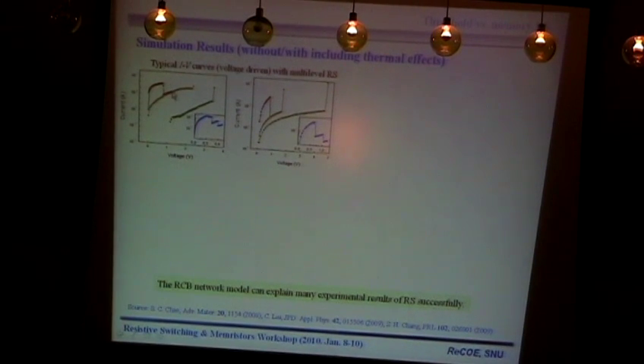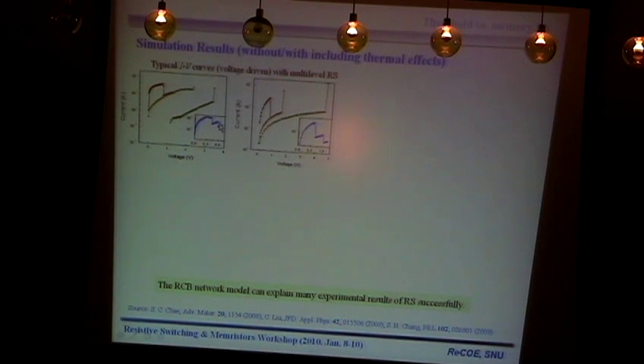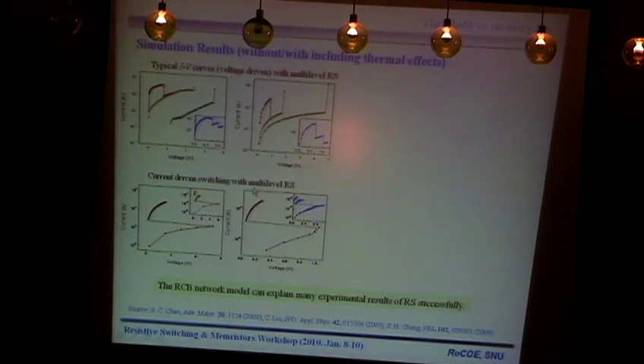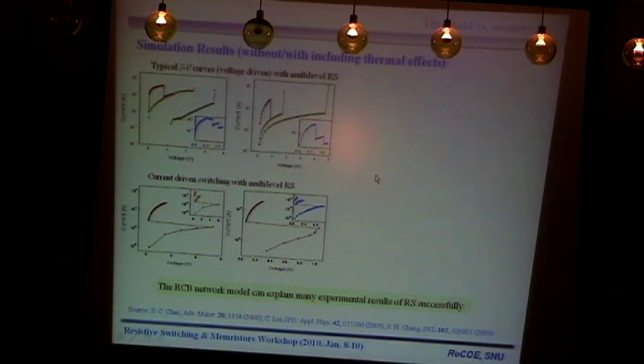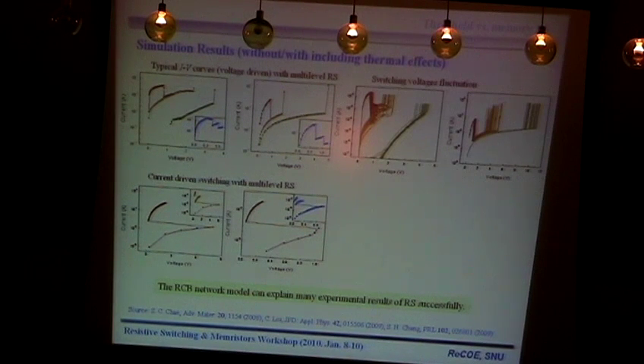First, this is the typical IV characteristic curve showing forming and the reset and set process. Sometimes it shows multi-step, multi-level switching. The simulation can show the same thing, and if you change the initial defect configuration a little bit, sometimes you get multi-step, multi-level resistance switching. Also, this is current-driven switching, which was first done by Samsung, and you can simulate the same multi-level resistance switching with current driving. A lot of people also reported a wide distribution of the switching voltages. The simulation can give exactly the same thing.